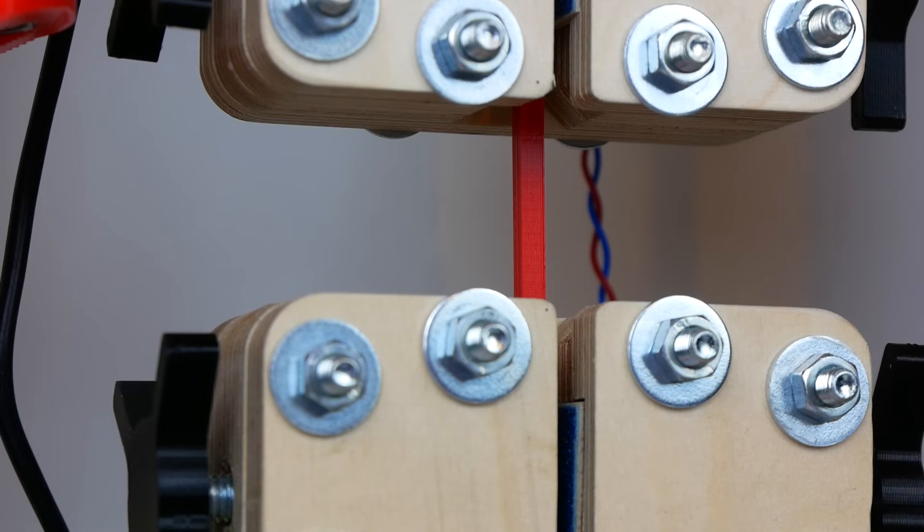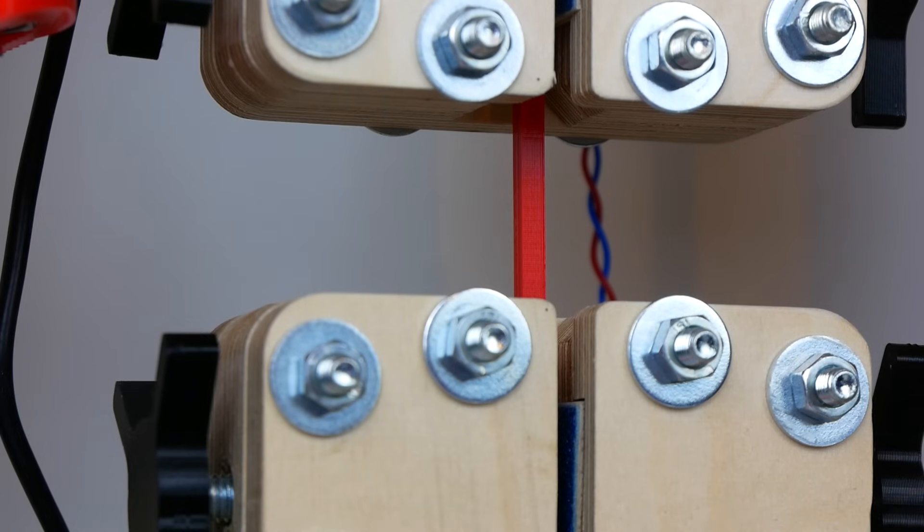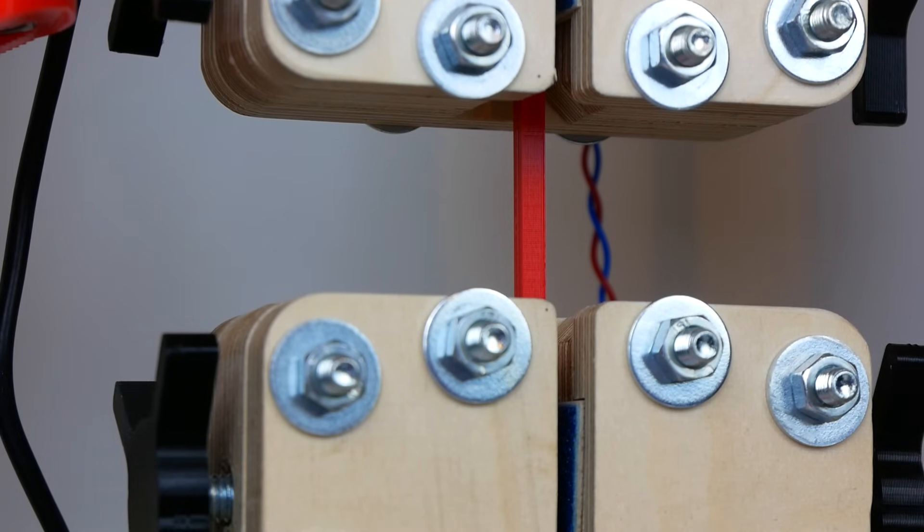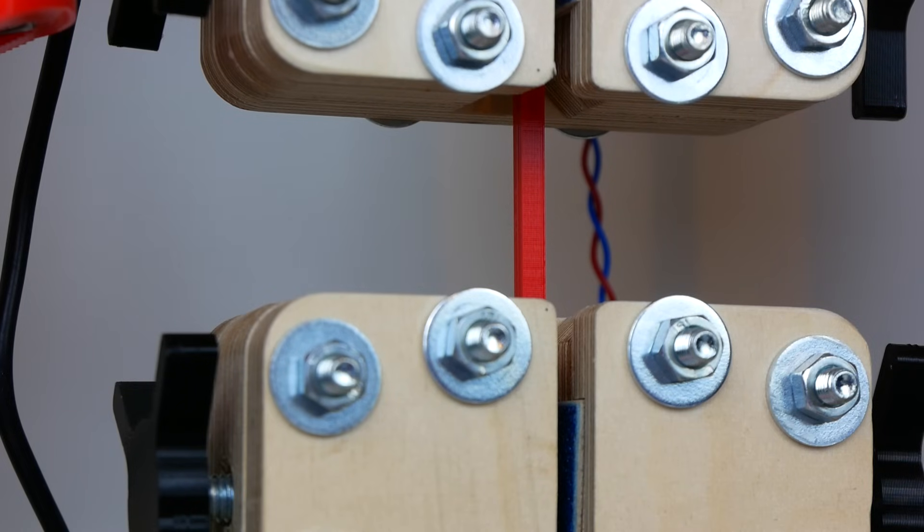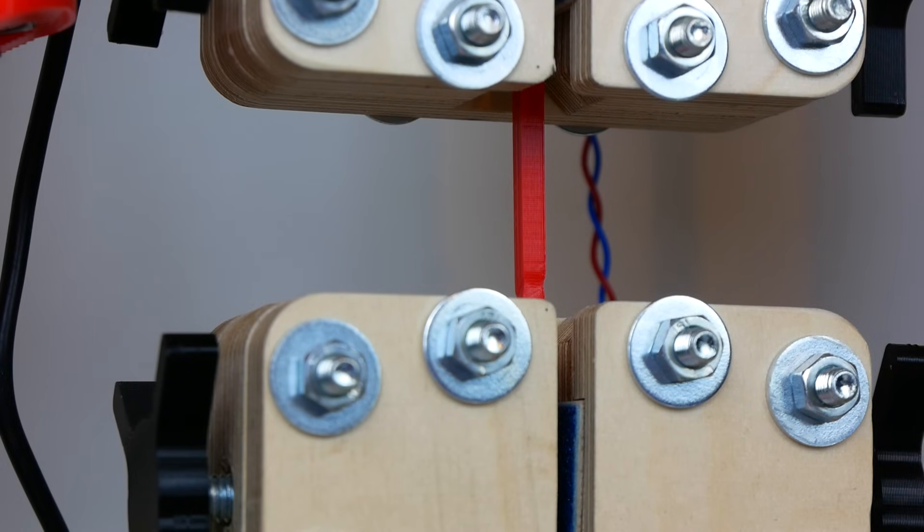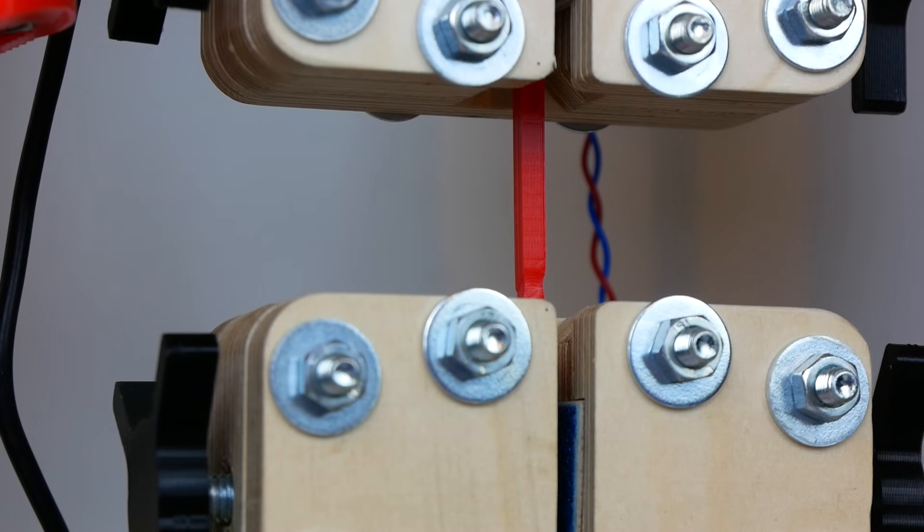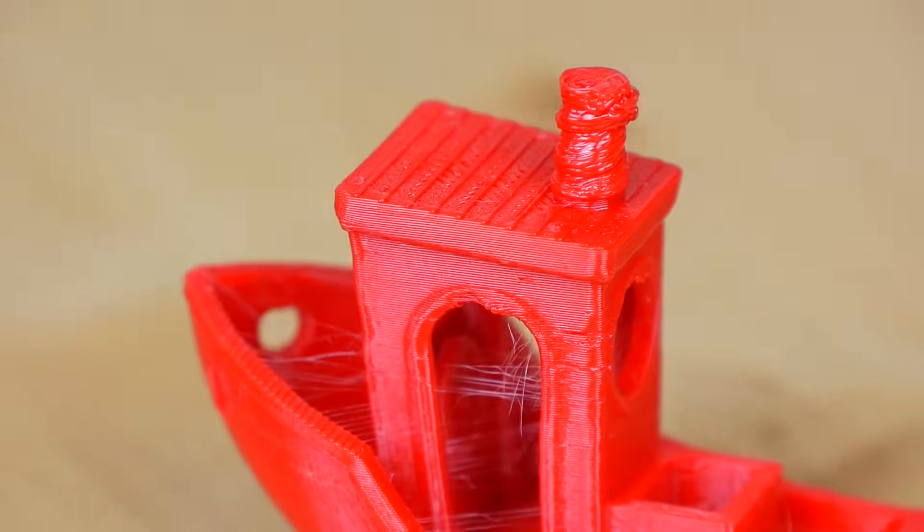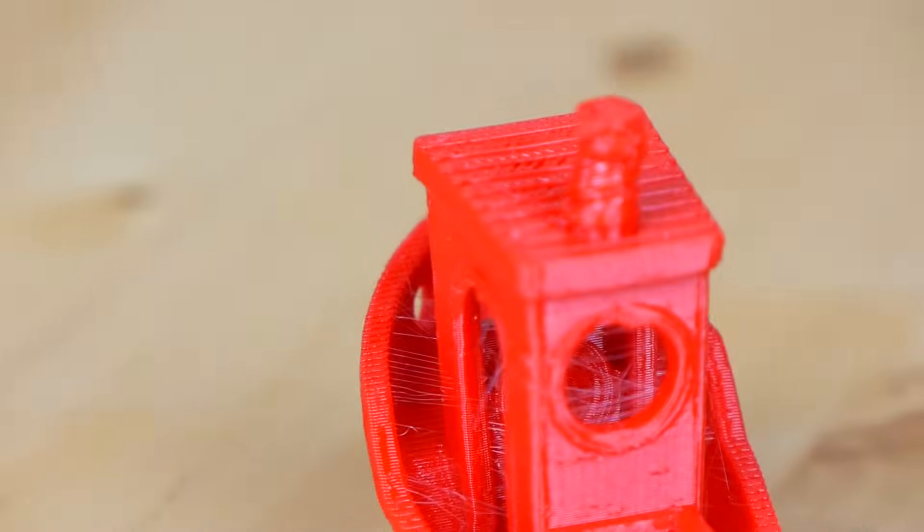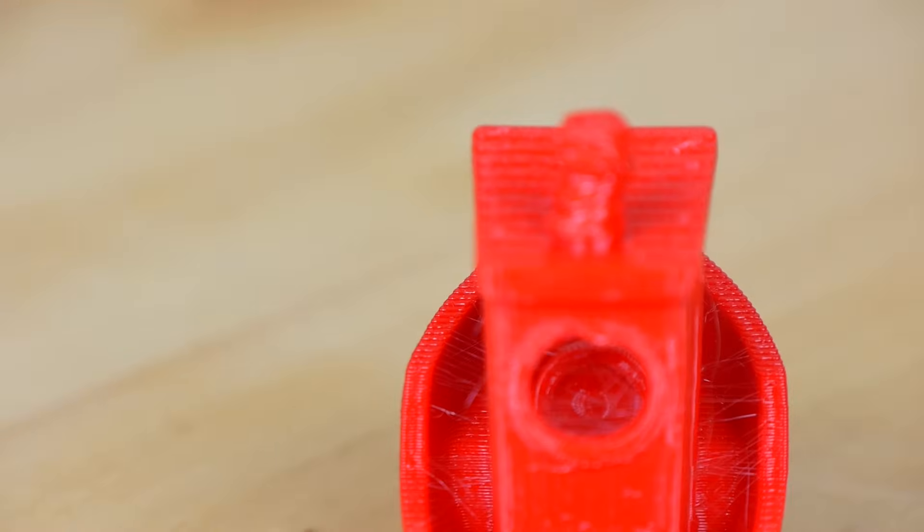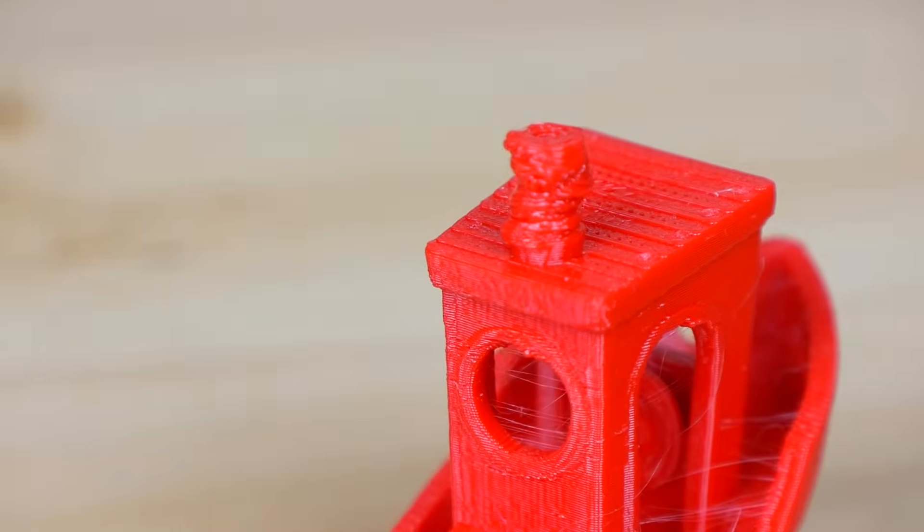I have printed all of the specimens with the part cooling fan running at 50%. I turned it off for one set of specimens, which resulted in more than 25% better layer adhesion. You might be thinking, hey, why do we use it at all? But if you print a detailed part without the fan on, you will notice that the print results get way worse at some details and the stringiness increases. This might be a good tradeoff for some parts, but generally I think you should have it turned on for the sake of print quality.